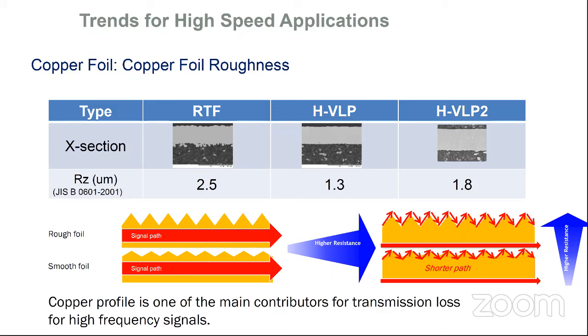And there's some adaptation of industry standards relative to roughness. So copper foil suppliers understand that their process setup would generate a particular copper foil profile. The drum side is typically always going to be very smooth by the nature of the highly polished stainless steel drum or titanium. But the side that's exposed to the anode, that's where copper grain refiners and how you control the actual rectification or current, which creates the grain structure, the nodulation, is a science that is very well controlled, and there will be different process setups to generate different roughness finishes, if you will.